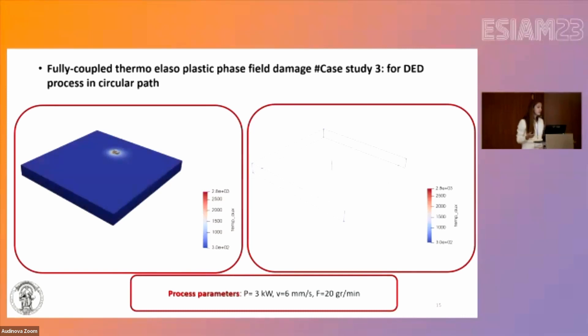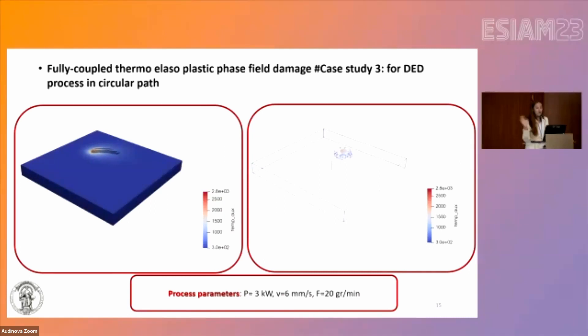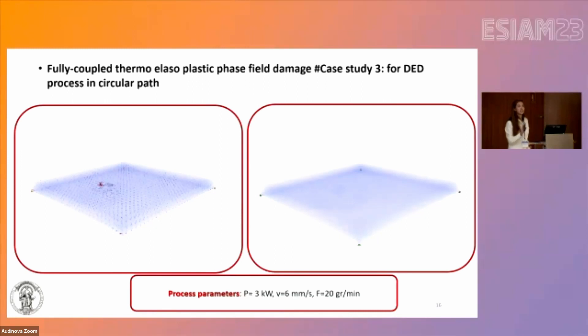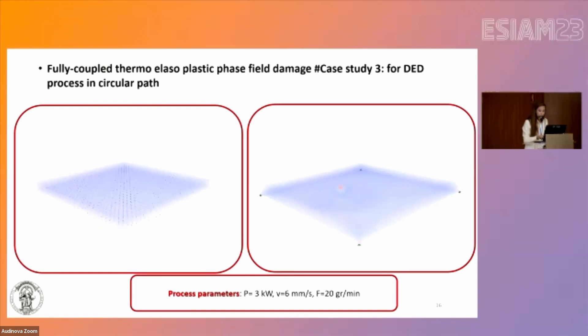The third case study is a little more complex, showing a circular path and how the adaptive mesh technique activates elements along that path. This slide shows the flux of the temperature, which plays a key role in fracture. In additive manufacturing, we don't have external forces causing fracture; the fracture is controlled by internal forces due to shear and thermal gradients. The temperature flux is shown here as driving the fracture, and the fracture propagation is captured using filters in the visualization.